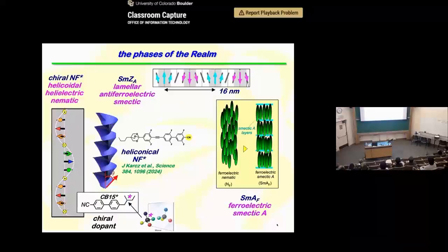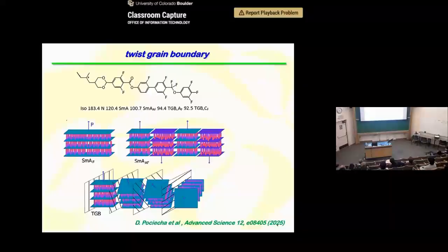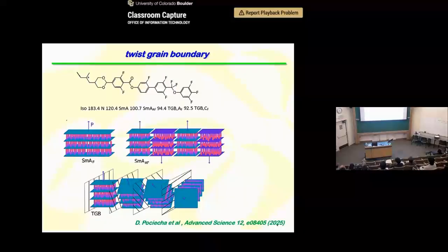Well, if you want to twist this, you can imagine a horizontal twist axis where the director is going like this, okay? But then that twists the layers. The layers don't like to be twisted. So then what happens is that you get a twist grain boundary phase. So the director will twist, the layers will fracture, and then you get these layers of screw dislocations which enable the layers to change orientation. So this transition to this TGB phase, the application of this twisting, is formally analogous to applying a magnetic field to a type 2 superconductor.